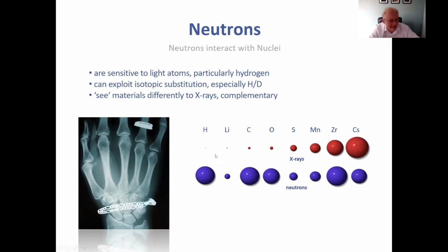So if you look at the scattering here, the red is the scattering by X-rays and the blue is the scattering by neutrons. We get very strong scattering from light elements like hydrogen, to a lesser extent lithium, carbon and oxygen, which you don't get for X-rays. So for X-rays, the scattering is dependent on the atomic number. And also we get differential scattering from elements that are close to each other, which is particularly important for transition metals. So we can differentiate, for example, between nickel and copper by neutron scattering, which is very difficult by X-ray scattering.